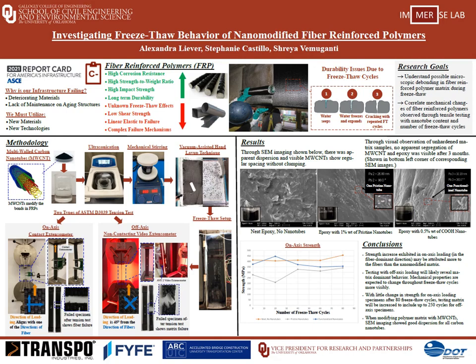Our research goals are to understand the microscopic debonding that is happening in the FRP through many cycles, as well as to understand how the number of freeze-thaw cycles and the concentration of carbon nanotubes affects mechanical properties. To achieve these research goals, we cast carbon fiber FRP plates with hand layup method and expose these samples to freeze-thaw cycles. To determine how mechanical properties had changed, tensile tests were performed on on-axis and off-axis specimens.